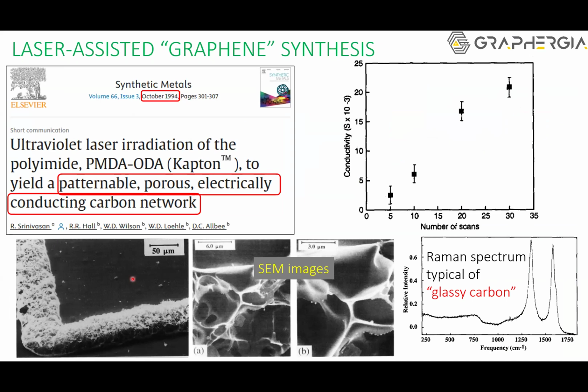For historical reasons, this is one, let's say, seminal paper published, you can see here, 20 years before the Tour paper, where actually the Kapton foil was decomposed by laser beams, producing highly porous and highly conductive graphenes. That time termed glassy carbon, because the graphene term was not so popular, but the physics and the mechanism behind all the discoveries that followed during the last years was known since that time.